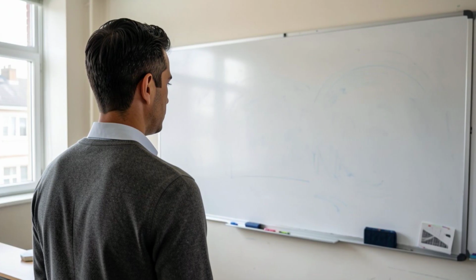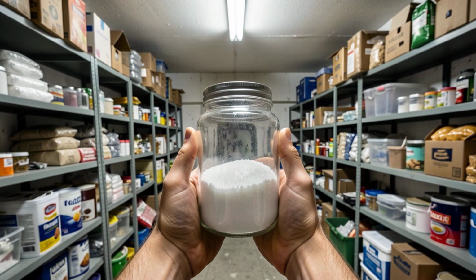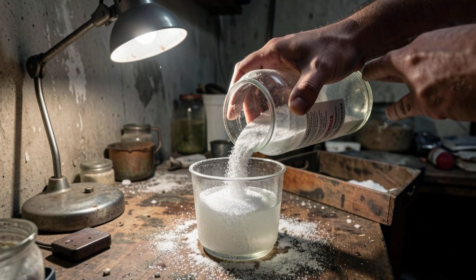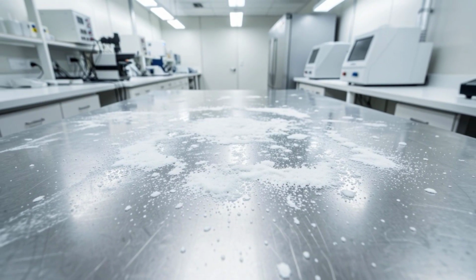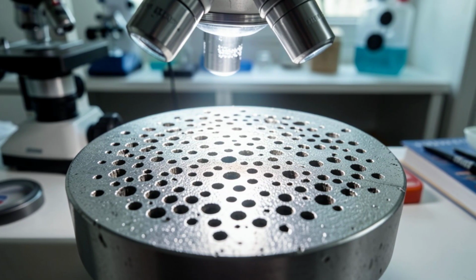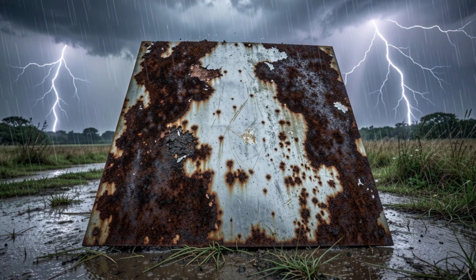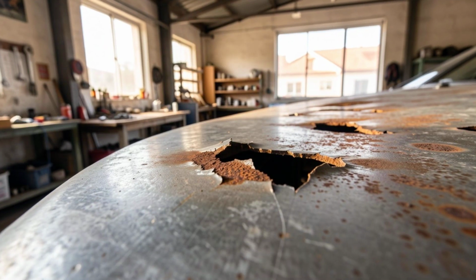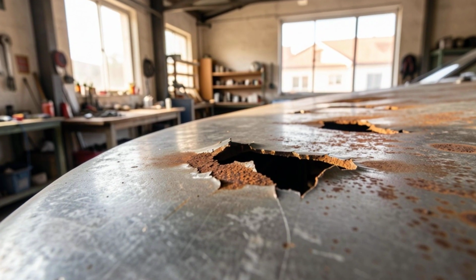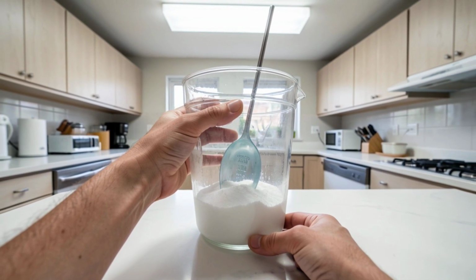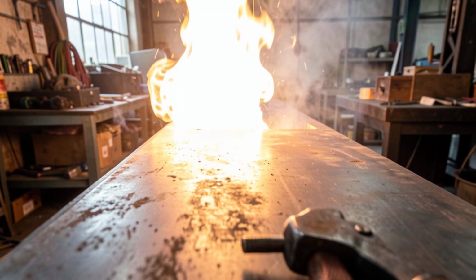And let me hammer this home one final time. Do not let anyone talk you into throwing salt into your solution to speed it up, because the chloride in salt does not rinse cleanly out of porous metal. It lodges itself down inside the fresh pits and triggers a hyper-aggressive corrosion reaction that will rot that panel out faster than it ever rusted in the first place.